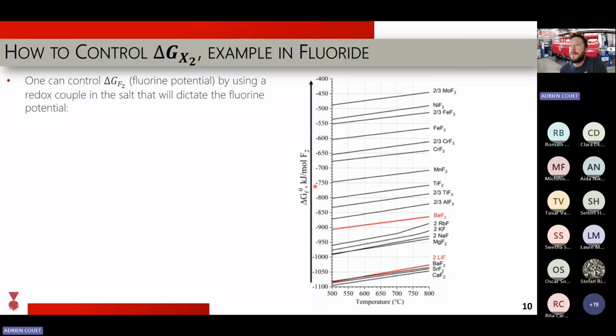So one of the aspects, which is more material-science-y, to look at corrosion is to use the Ellingham diagram. You have an Ellingham diagram on the right-hand side here. This shows the free energy of formation of some compounds in salt as a function of temperature. Here it is for the fluorides. The lower the compound is in this plot, the more stable it is. So you have a lot of very stable salts: barium fluoride, lithium fluoride, sodium fluoride. Those are very stable. And then you have less and less stable elements. For instance, molybdenum, and if you were to keep going like this, gold and so on, would be very unstable fluorides. They would prefer to remain metallic. So the important part here is to have your partial pressure of fluorine be lower than the line of an element. If that is the case, then it means the salt is reducing enough that it's not going to lead to the corrosion of this specific element.